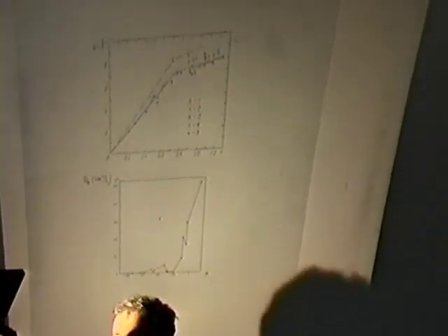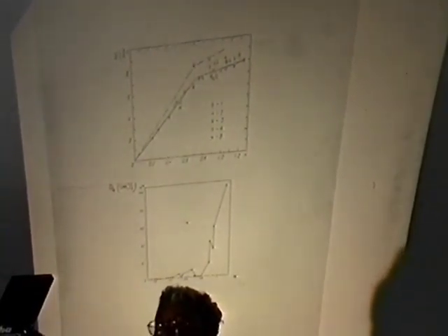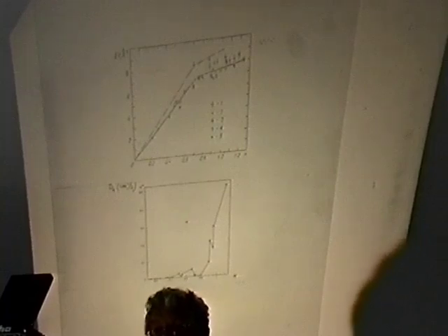Some suspicion of the existence of a transition at X equal to 2/3 at room temperature can be observed in these graphs. This graph is just the behavior with X of the diffusion coefficient of hydrogen in palladium. And this other graph is the behavior of the unit lattice volume as a function of the loading. You can see that the palladium lattice grows quite a lot in the beta phase, and instead the increase is smaller in the gamma phase. Of course, the existence of such a discontinuity could give a suspicion, not a proof, that a phase transition could occur.